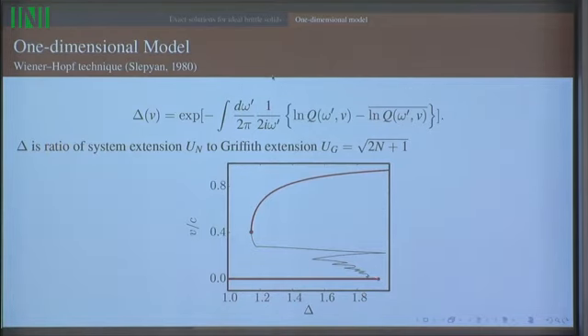It's at this point that the system finally becomes linearly unstable and would begin to run no matter what. Incidentally, many computer approaches to this and similar models have gone along here and then concluded that there did not exist running solutions, and then they've gotten to here, and the system at this point is subject to a whole bunch of not numerical instabilities, physical instabilities where the crack can't run stably, and it actually will often, in a numerical implementation, self-arrest. So if you simply do numerical studies of a typical crack system by building it on the computer and then pulling on it, it's been very common to conclude from that running cracks didn't exist at all. Because unless you knew that this branch was there, you wouldn't set up the initial condition so as to find it. And the computers tended not to find it automatically.